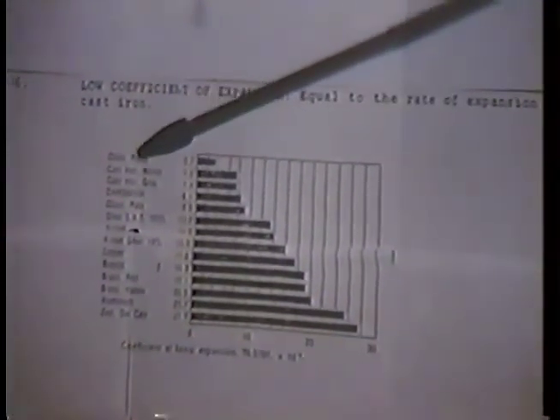And you'll see on the chart here, this is just a chart comparing coefficients of expansion of everything from Pyrex glass down to die-cast zinc. Chromium and cast iron, right here, you'll see are very comparable to one another in the coefficient of expansion. So you have the chrome layer and the cast iron layer, and they're not working against one another as the engine heats up or cools down.